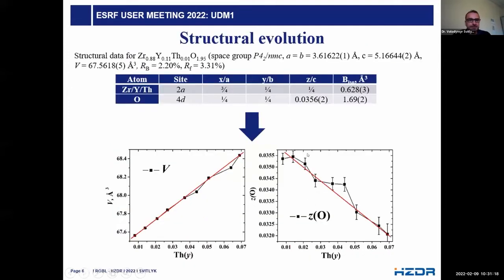Actually, in this tetragonal zirconia, you have only one parameter to refine. This is the z of the oxygen atoms. So when you introduce thorium into this system, as expected, you increase the volume, but also what we have found is that upon thorium intake, the z of the oxygen atom systematically decreases.